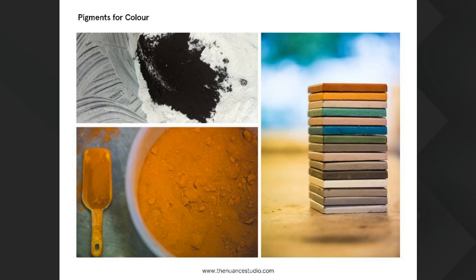UV resistance is generally measured by color fastness. The highest color fastness is 8, and all of these pigments belong to the 7 and 8 category. If I have to give you an example of color fastness, let us say you have clothes which tend to fade over a period of time, because the color fastness of these clothes would be maybe around 1, 2, or maximum 3. So that is the reason you actually see fading. But these products with the homogeneously mixed colors, you would be able to use them in indoor and outdoor situations absolutely without any problem, even in erratic climatic conditions.